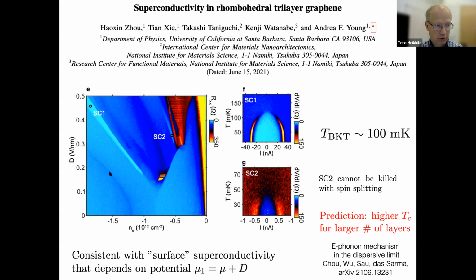And then what they find is these superconducting lobes. So this SC1, and then there's another one here where there is a zero resistance state below some critical temperature. The largest critical temperature that they see is actually around 100 millikelvin. So smaller than this 4 Kelvin, but this is most likely due to the fact that there are only 3 layers.